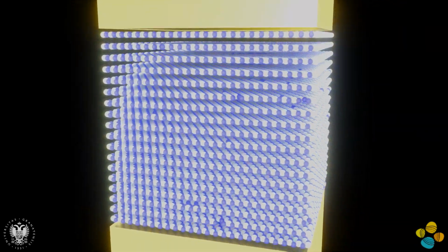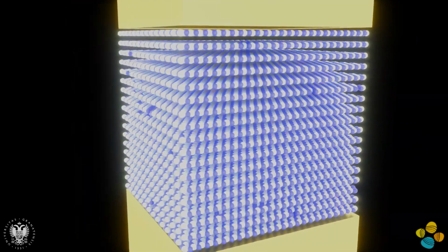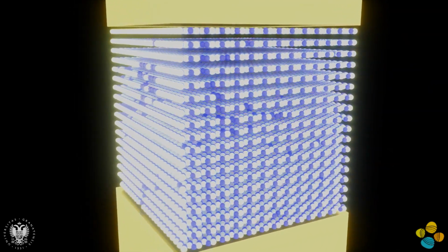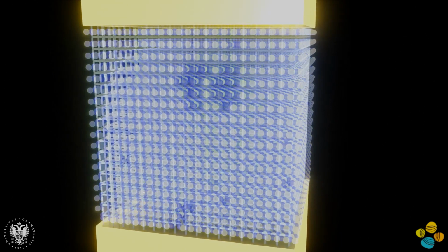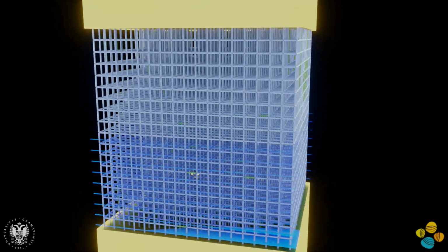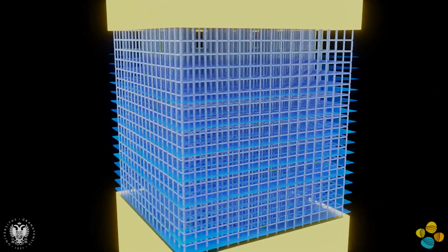In our simulator, we represent the dielectric conduction properties with a three-dimensional network of resistances connected to the metal electrodes. Since our dielectric is 6 nanometers thick and approximately consists of 18 layers of hexagonal boron nitride, for symmetry reasons we consider a cube with 18 layers of resistances in each direction.